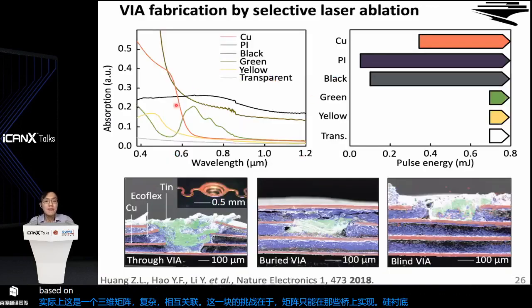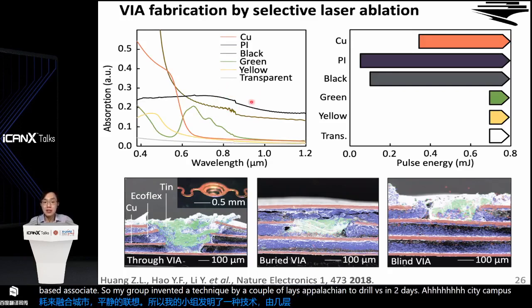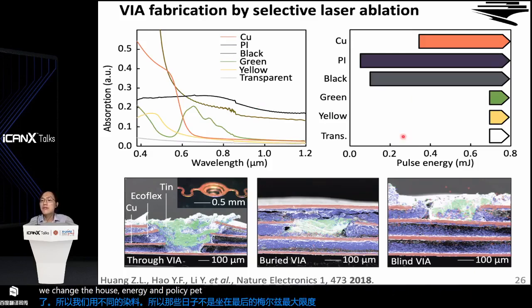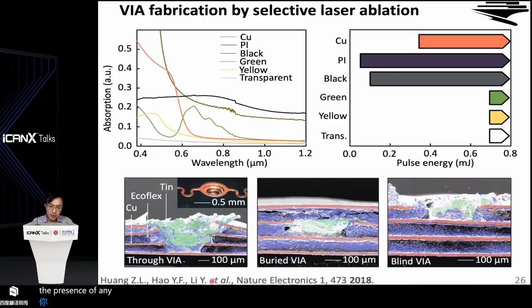So my group invented a technique by coupling laser ablation to drill vias into these silicone-based elastomer substrates. We use different dyes to dope these silicone elastomers to maximize absorption, and then we tune the pulse energy and the pulse repetition cycle. So eventually, we were able to selectively remove any kind of material in the presence of any others. At the bottom here are images showing 3 typical via structures.